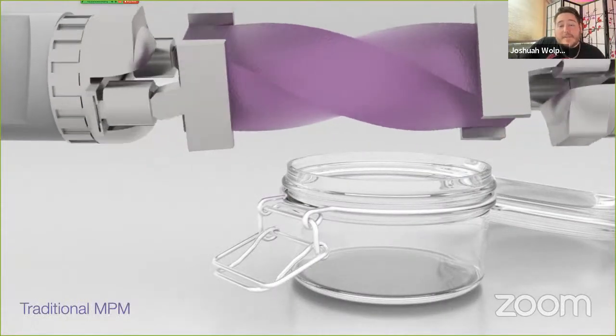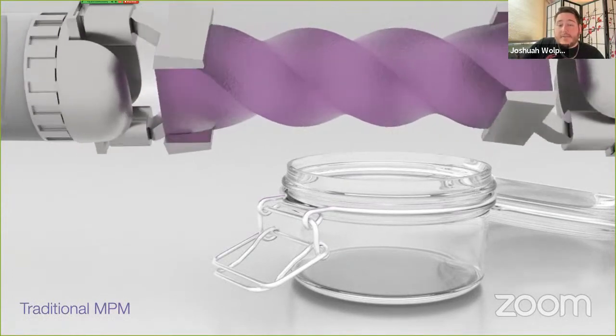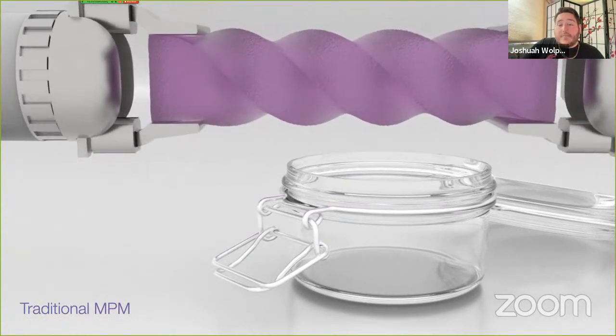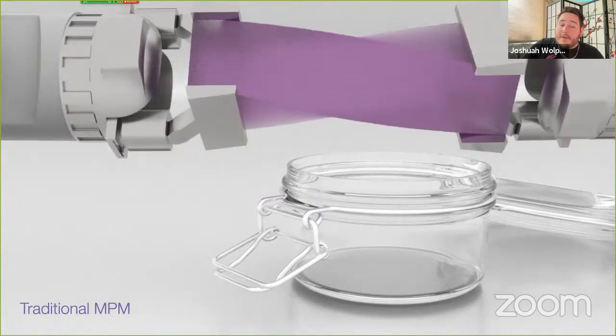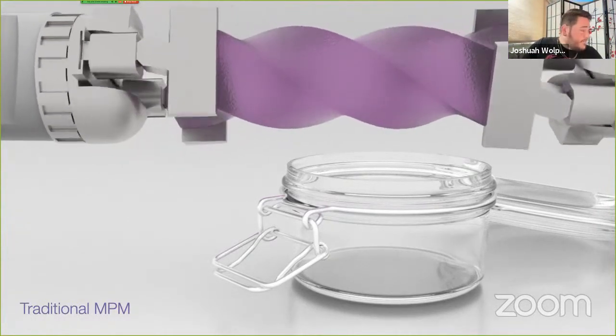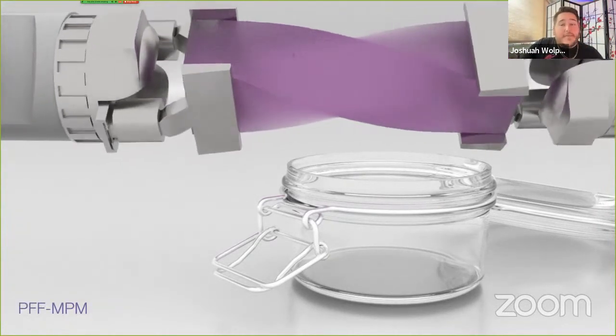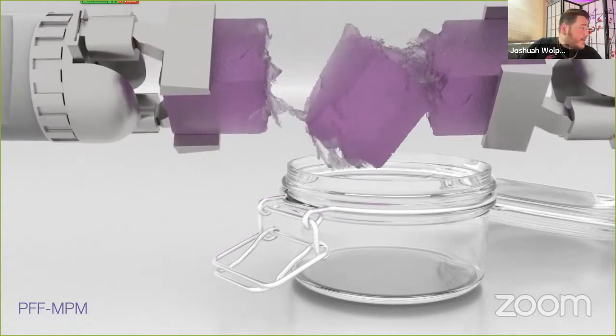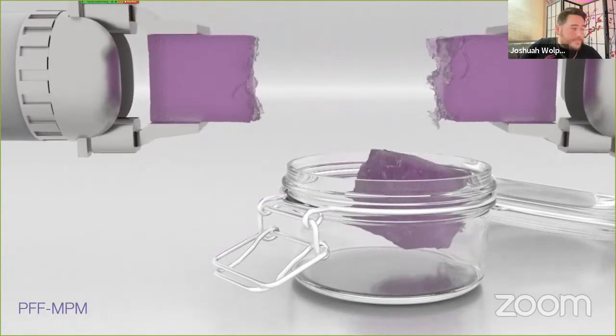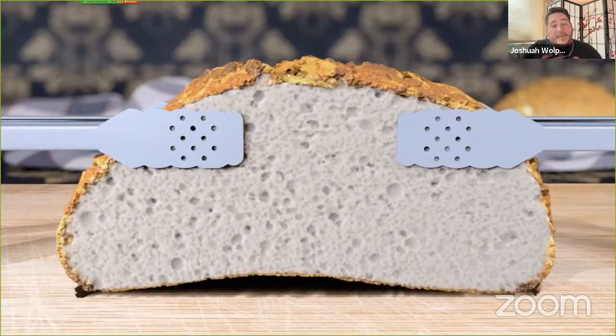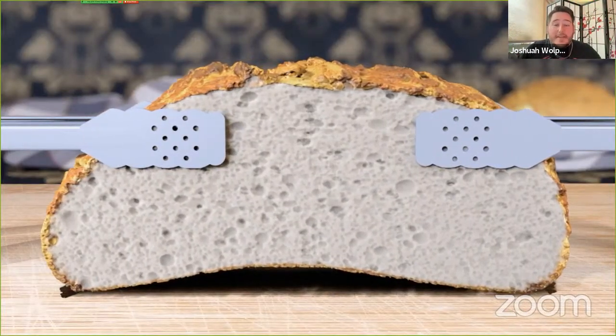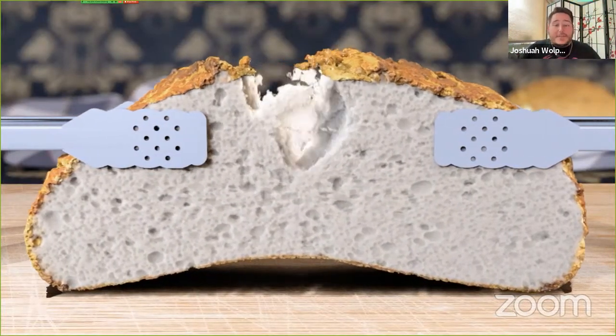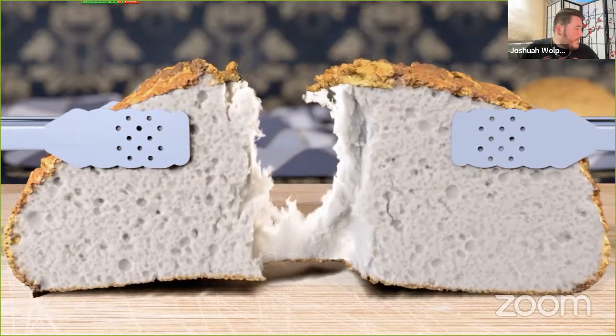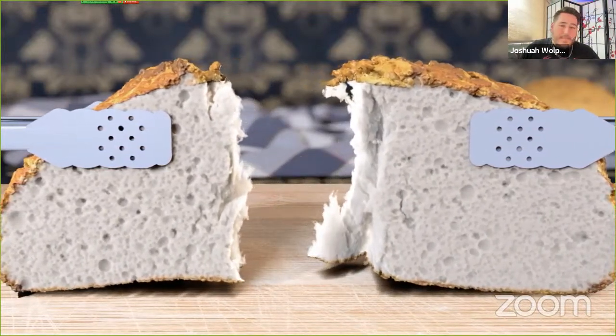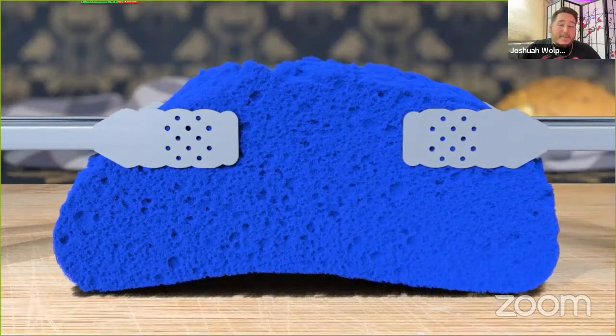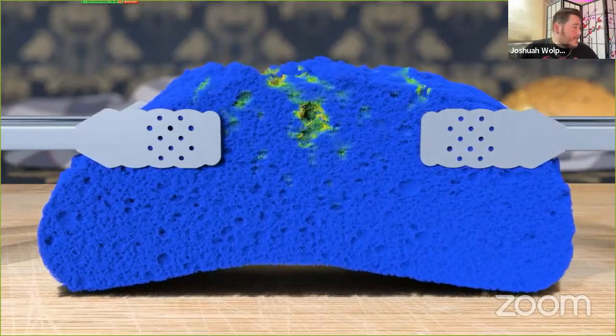Similarly to before, we twist a Jello bar with traditional MPM to show that in some cases, numerical fracture can't produce the desired behavior, let alone any fracture at all. And fortunately, with PFF-MPM, we achieve the desired fracture pattern as the Jello twists. And finally, we slowly tear a piece of bread to reveal the intricate fracture patterns and dynamics we associate with fresh bread. And we again visualize the phase field to show off all the small fractures invisible in the render view.